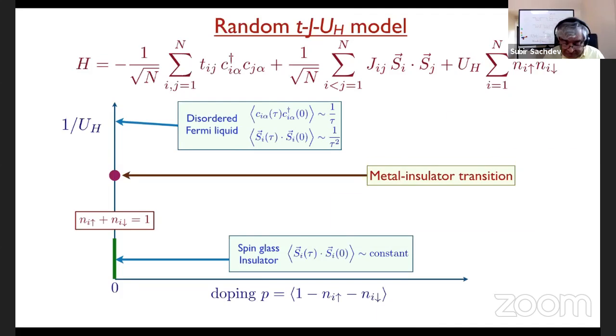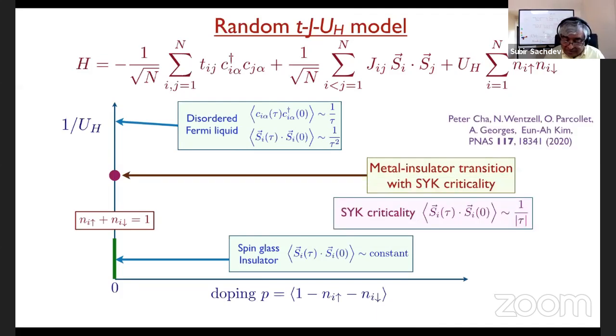So that metal insulator transition has been studied in some very beautiful recent work by Cha, Wentzell, Parcollet, Georges, and Eun-Ah Kim. This is done by solving these self-consistency equations that I showed you earlier, schematically, for both the spin correlations and the electron Green's function, using quantum Monte Carlo in the replica diagonal sector. And after quite a lot of hard work, they've been able to solve it. The half filling helps. Extending it to finite doping requires, even in that method, there are sign problems, but I think there are going to be interesting results in that direction too.